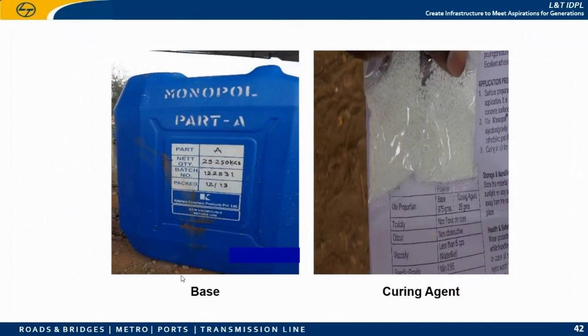So, sir, you can say, when the code itself is allowing, why do I have to go for crack sealing? Because these cracks are like a gateway opening where you are welcoming the moisture to penetrate, and welcoming carbon dioxide to penetrate inside, because concrete is a porous material, so it will easily enter and increase the rate of corrosion. It will affect the good structural concrete and the good structural steel. So that is why it is always necessary to seal the surface crack.